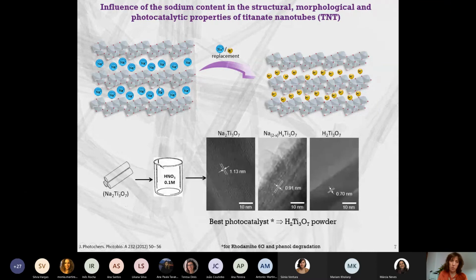In fact, to have these materials, we just need to put our titanate nanotubes, nanowires, or nanorods in an acid solution, control these conditions, and then we can control the dimension of this interlayer. And with this, we know the amount of sodium or proton that we have in this material. And of course, at the same time, we are preparing some materials with different photocatalytic activity for the degradation of pollutants.